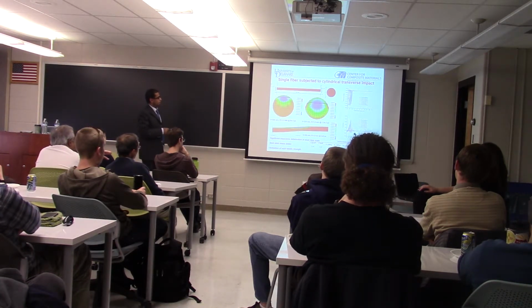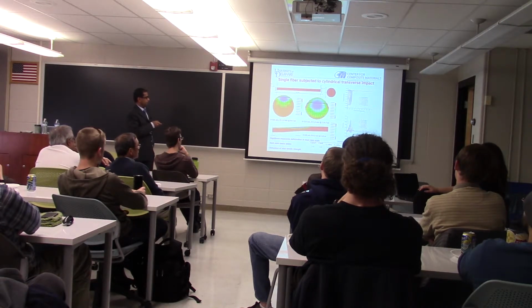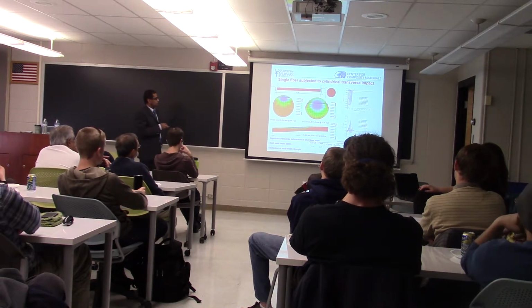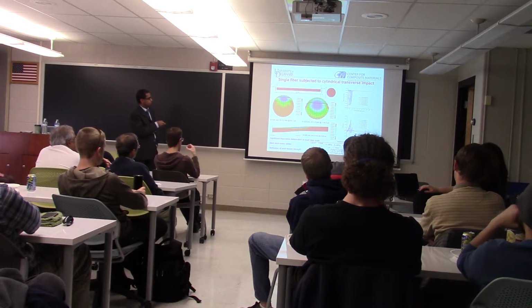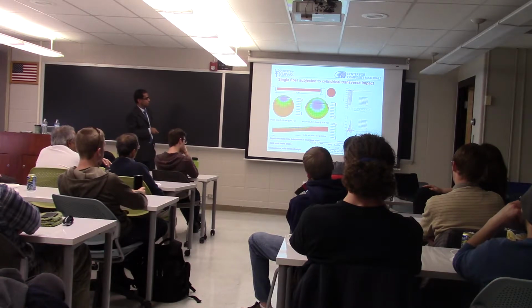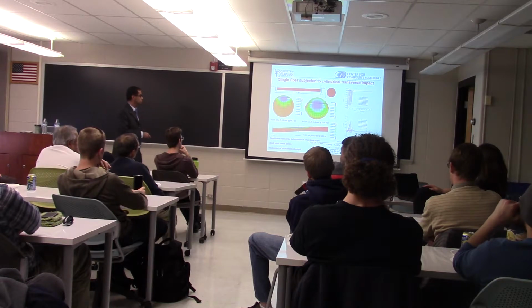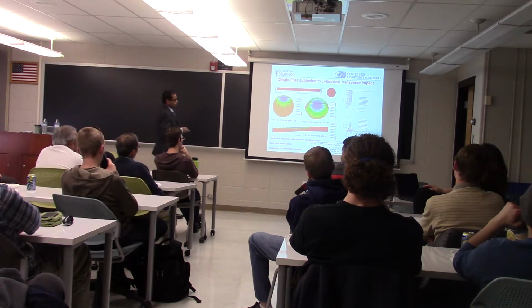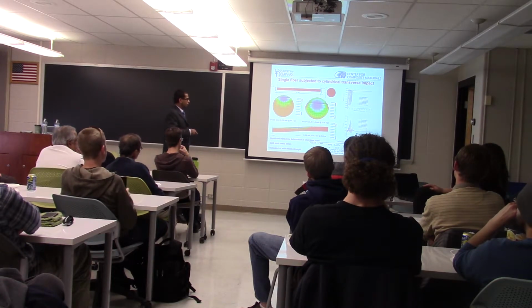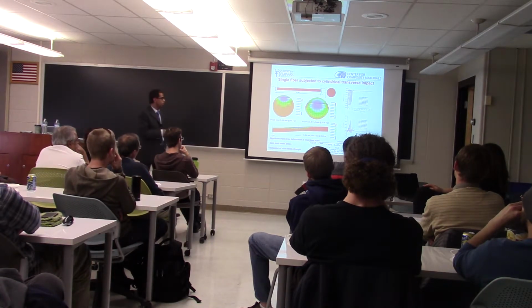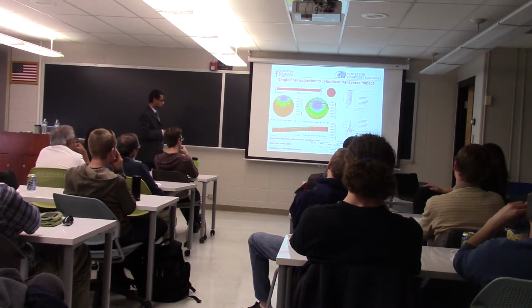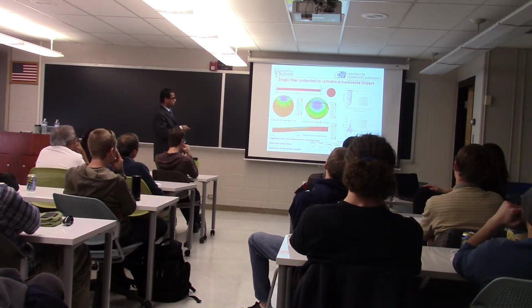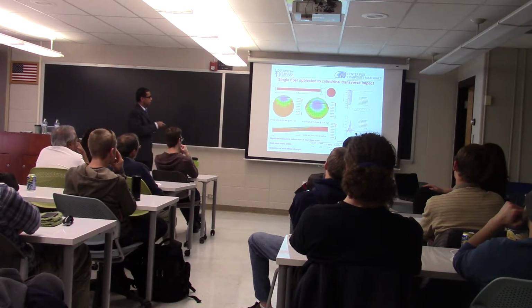So to our knowledge, there are no single fiber impact experiments reported in the literature. So we've modeled this single fiber impact at the midspan with a rigid cylindrical projectile of different radius and impact velocities using a 3D finite element model with the commercial finite element code LS-DYNA. The model predicts, during short time scales, significant transverse compressive deformation in the fiber, and the model also indicates multi-axial stress states in the fiber. The magnitude of these compressive strains depends on the impact velocity.